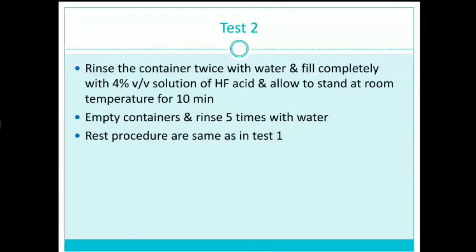Then test 2, how to perform test 2. Rinse the containers twice with water and fill them completely with a 4% volume by volume solution of hydrofluoric acid and allow to stand at room temperature for 10 minutes. Empty the container and rinse 5 times with water, and do the rest of the procedure the same as mentioned in test 1.